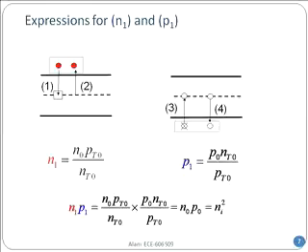The trap occupation, how it cancels? And N0 and P0. Why am I writing it as Ni squared? Because remember, this is in equilibrium. So the electron concentration and the hole concentration, regardless of whether there is trap or not, if there is trap, good, if there is no trap, that's even fine, it's always equal to Ni squared. That's the mass action, right? Remember, that's why I said it's very important. It really doesn't depend on whether it's doped, undoped, whether acceptor, donor, trap, doesn't matter.